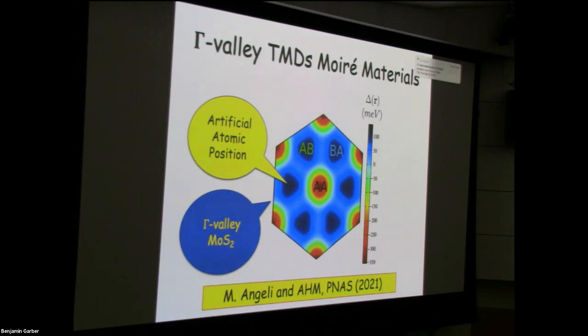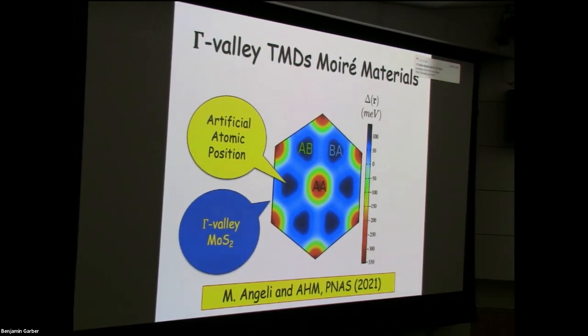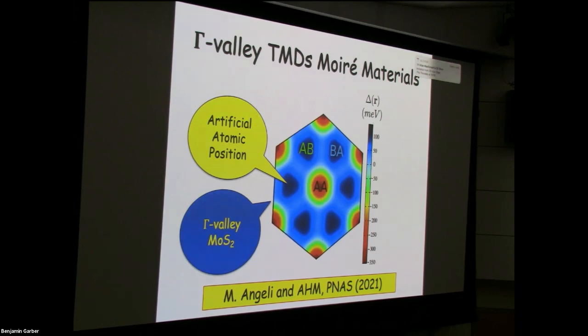this is another possibility that has not been realized experimentally so far, as far as I'm aware. This is 2D semiconductor layers stacked so that they're close to being right on top of each other. It turns out that in that case, the low energy states in the valence band, like in bulk materials, are near the center of the microscopic Brillouin zone, not near the edges. And when you make a bilayer of two identical materials, it forms bonding and antibonding states, and it acts basically in the end like a single layer. Importantly, it is a single layer where the effective potential has honeycomb lattice symmetry instead of triangular lattice symmetry.